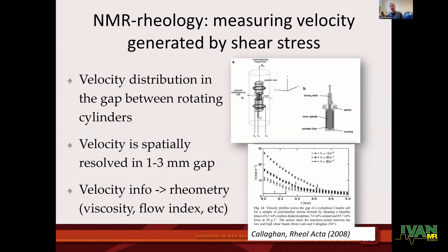When it comes to rheometry, NMR rheometry is actually quite an amazing field where, most frequently, you build some sort of a Couette cell inside your NMR spectrometer. And so you place your fluid of interest between two rotating cylinders, you introduce shear stress, and you measure velocity within the gap between those cylinders. So we're talking about a gap of maybe 1 to 3 millimeters, and you measure velocity, spatially resolved, obviously. And it can give you lots of interesting information on your sample properties and behavior.